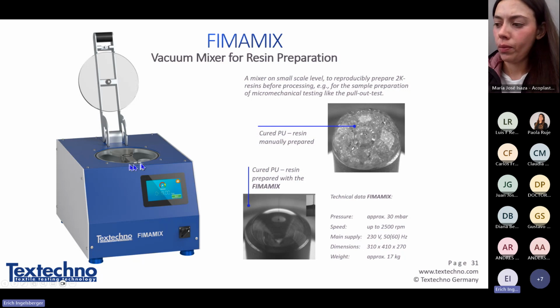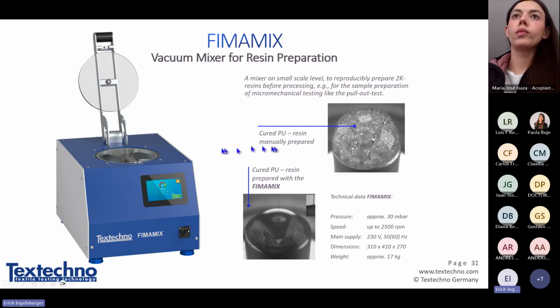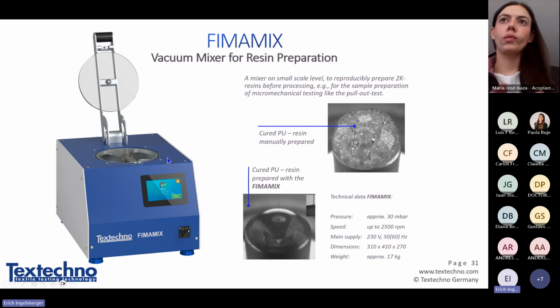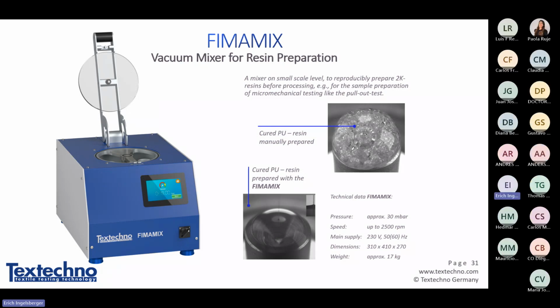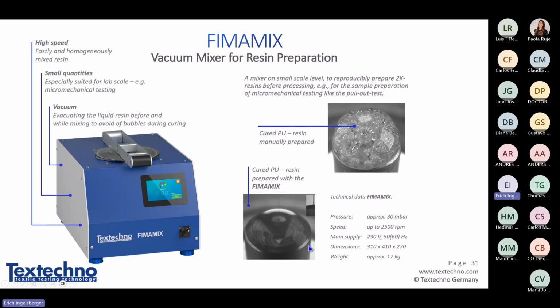This is double action, with 2 containers inside. You will see a video running in 1 second. By using the evacuation of air, the vacuum mixer takes out the humidity of the matrix and thereby prevents bubble creation. As you can see here, this is the same matrix with bubbles, manually mixed, compared to mixed with our FIMAMIX system. We can close the lid here.